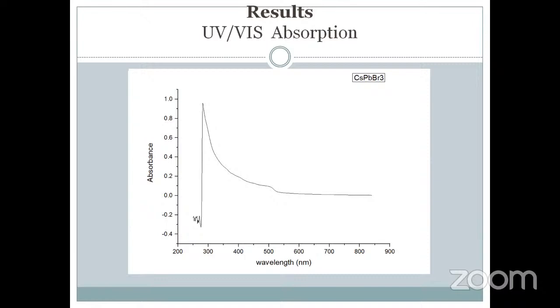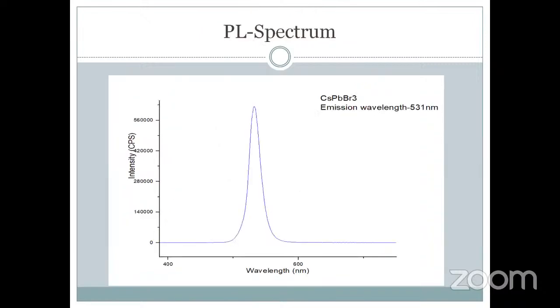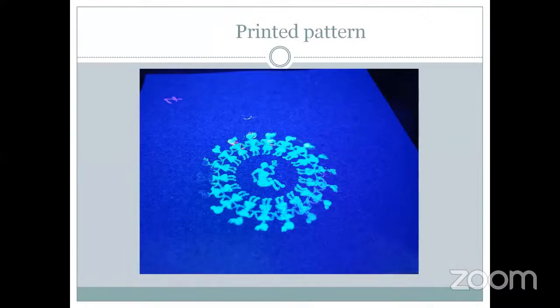It is clear from the graph that the absorbance is around 1, and the band gap was found to be 2.355 electron volt. Now again, I have shown the PL spectrum of CsPbBr3. The PL spectrum was recorded using a 367 nanometer excitation wavelength, and it shows a single sharp peak at 531 nanometers. Here is the image of the printed pattern. Here's the image of the pattern printed over a black substrate and recorded under UV light of 367 nanometers.